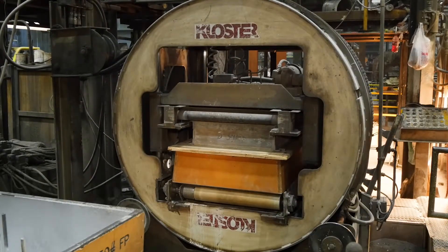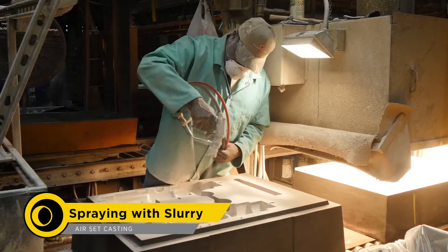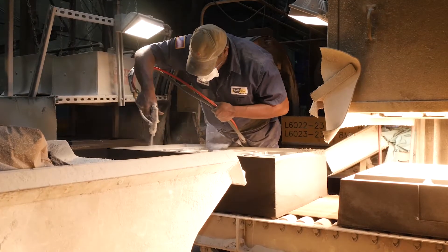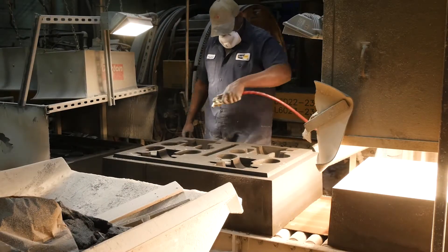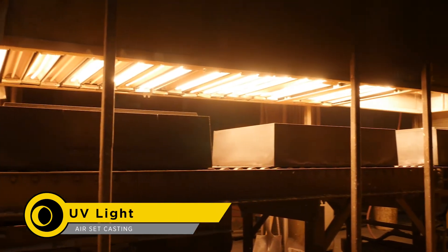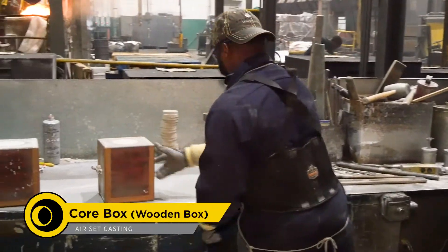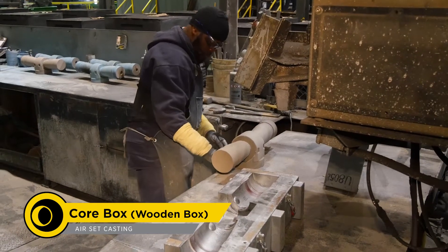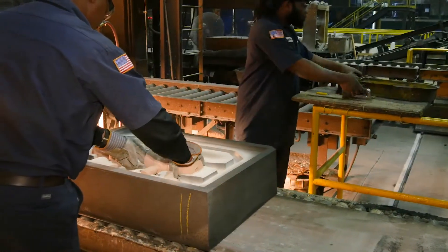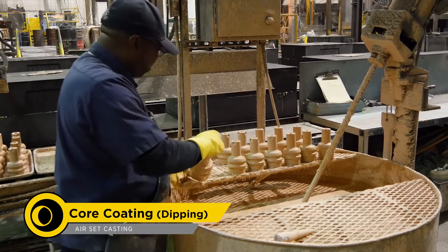The piece is then flipped and removed from the box. The internal passageways of the mold are carefully sprayed with an inert ceramic slurry, similar to that used in the investment casting process. This seals small voids in the sand and helps give the casting a smoother finish. The freshly applied slurry is then controlled dried using ultraviolet light. On an auxiliary line, workers are using the same process to prepare the sand cores, which will be placed in the mold cavities to create the internal passageways to the valve body or retainer. The cores are first prepped with a ceramic sealing slurry to provide a smooth casting surface.